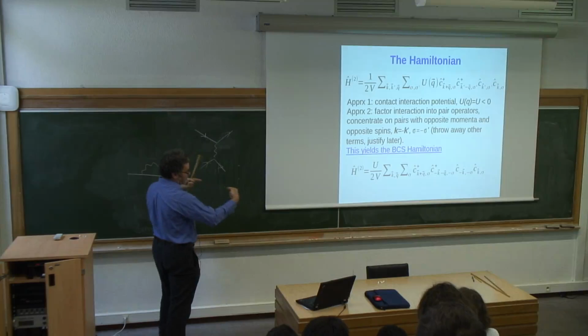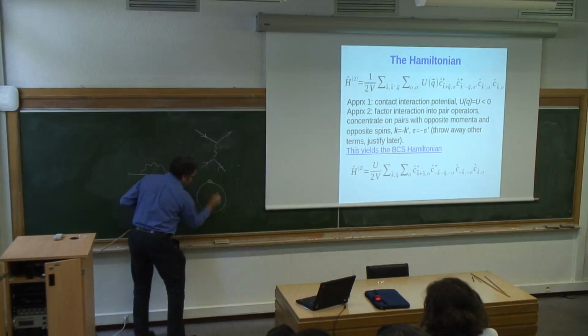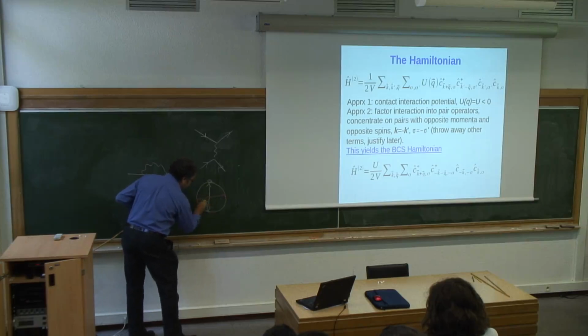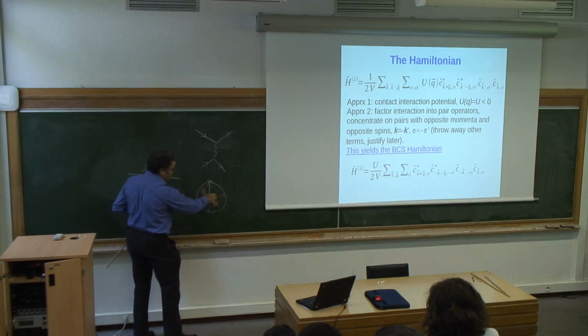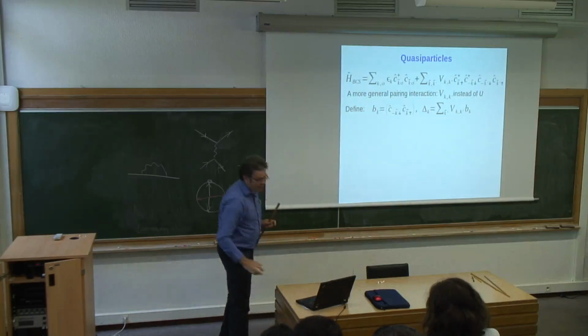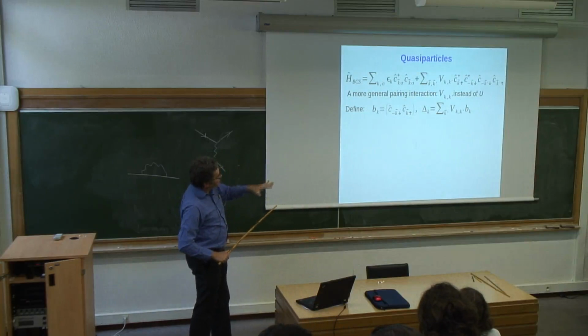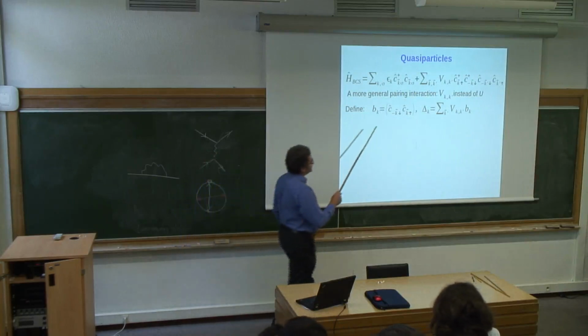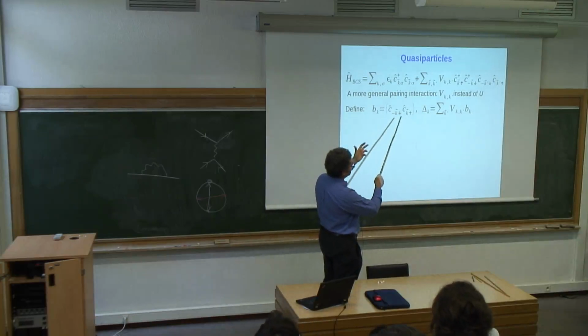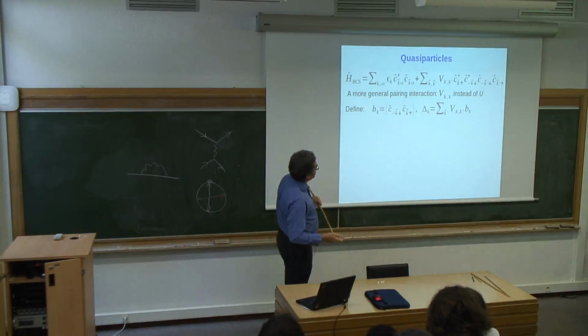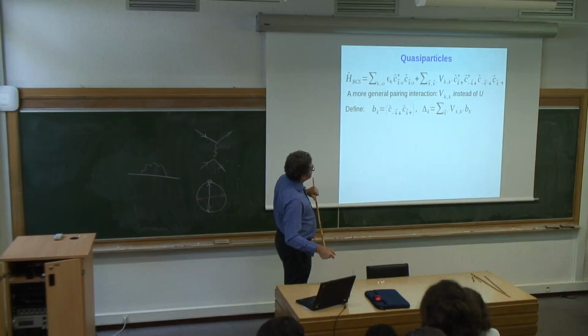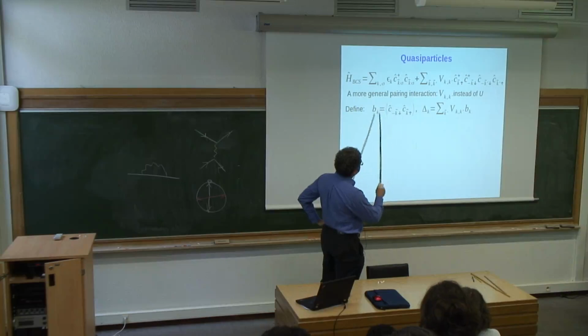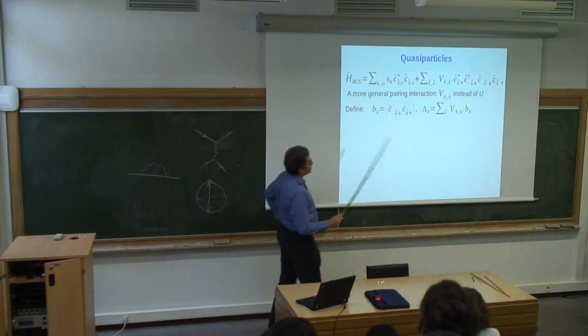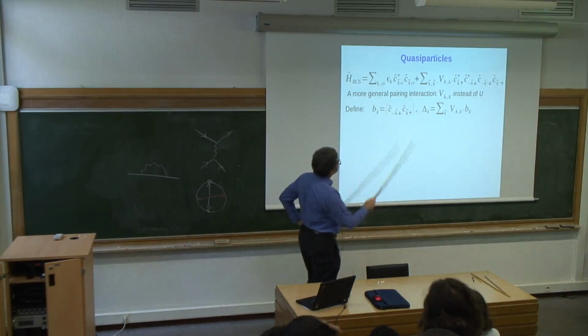So these two particles will have counter-propagating momenta and will be somewhere here on the Fermi surface. And then this process will describe scattering to a state near the Fermi surface with some other counter-propagating momenta, and they can be in arbitrary configuration relative to each other, right? So if you start with that, then you can derive a simple mean field for this Hamiltonian. You can take that operator that we introduced for pair creation and, given that we have many particles, you expect that this operator will acquire a non-zero average. You can define a C number, which will be an expectation value of that operator. And don't ask me how an operator which is not particle number conserving can have a non-zero expectation value.